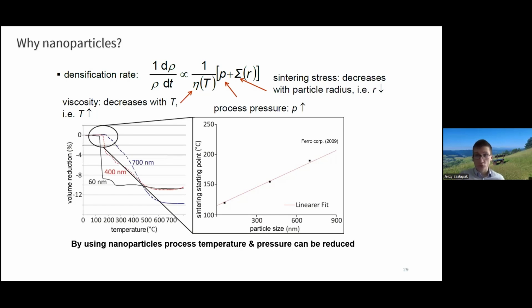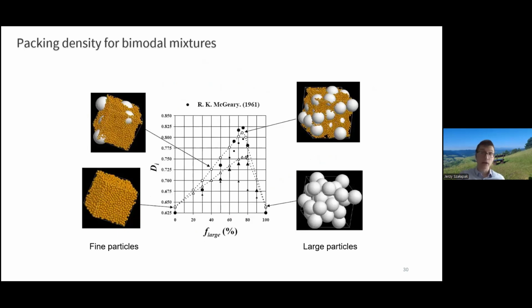But SEM and EDS photos showed that there was quite a high amount of organics within the layer, impacting the conductivity, because the conductivity was quite similar to soldering, and the mechanical parameters. And that is why we used a mixture of two sizes of silver particles: the nanoparticles mentioned earlier and silver microplatelets. Conducted tests confirmed McGeary's work that you can see on the slide really works. So the lowest porosity was achieved with 25% of the silver nanoparticles and 75% of the microplatelets. It is also worth mentioning that this approach nicely works on a bigger scale or in different materials, so for example, in adhesive preparation.